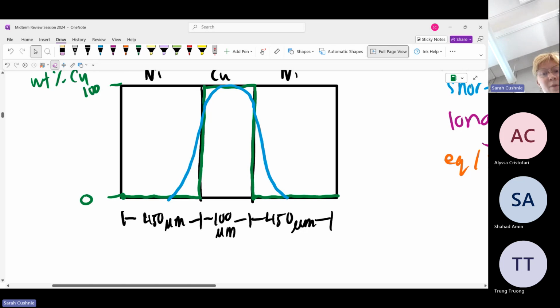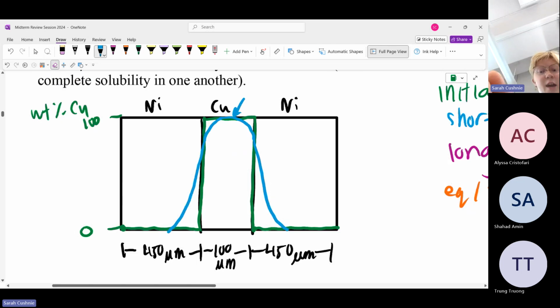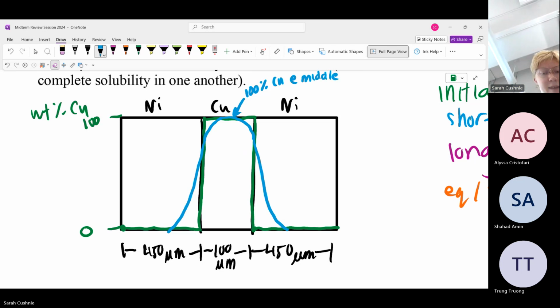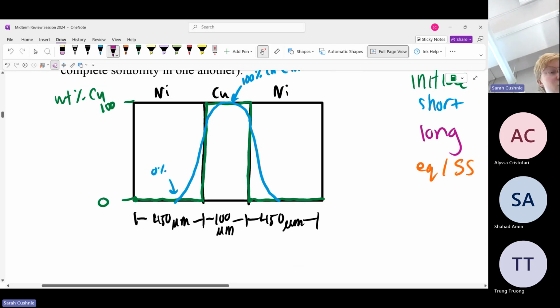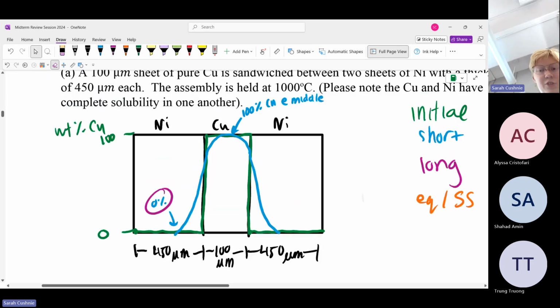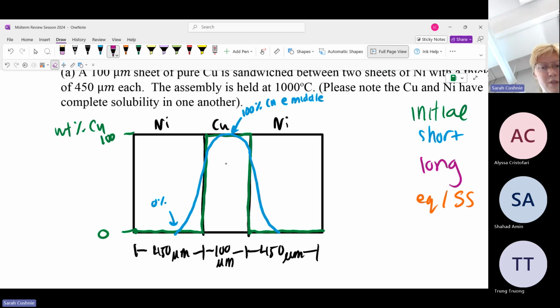Note that because we're at a short time, the big things to note are that we still have 100% Cu at the middle, and we still reach 0% copper in the nickel region. So it hasn't fully diffused yet, it hasn't gotten all the way, but it's working there. When we're talking about the long time, this process has just continued a bit more, but we no longer have these two standards. That's the differentiator between long-term and short-term: now we no longer have the initial conditions present. So it's going to look something like this.